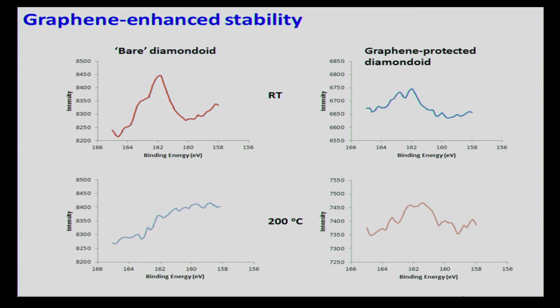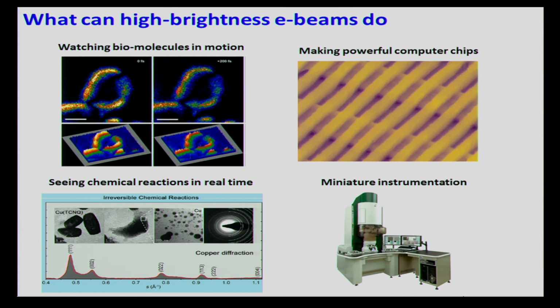What we show here is the XPS spectra of the sulfur. Basically, it's a signature of whether the diamondoid exists on the surface. You can see that with the bare diamondoid at room temperature, you have a very sharp peak indicating they are on the surface, but when you heat it up to 200 degrees, the peak is gone. When you have the graphene protected diamondoid, initially you also have the peak, and that peak is preserved when you heat it up to 200 degrees, showing that the species is confined to the surface by this graphene coating. So we think that we're on the right track to create a really stable and monochromatic, single color electron source.